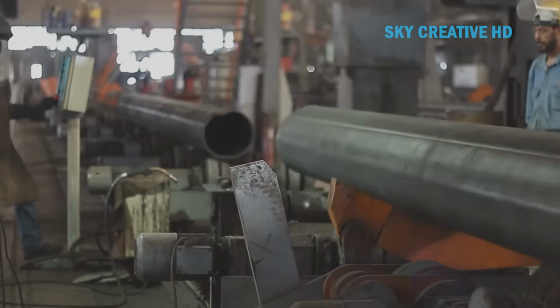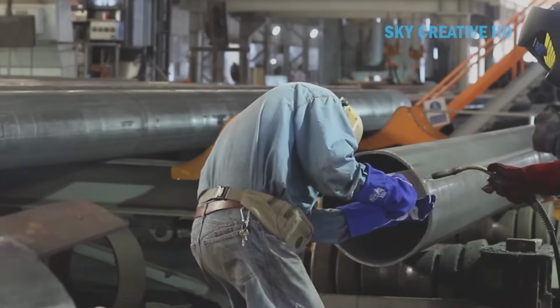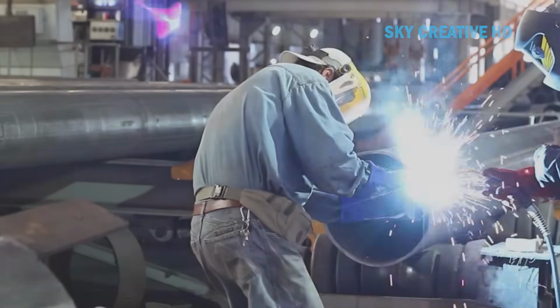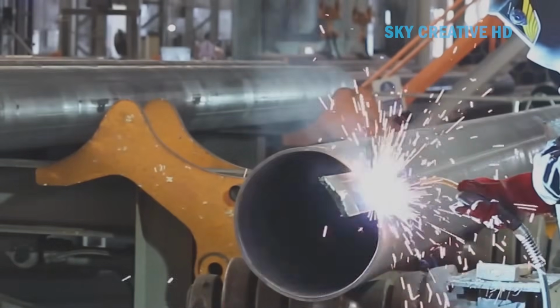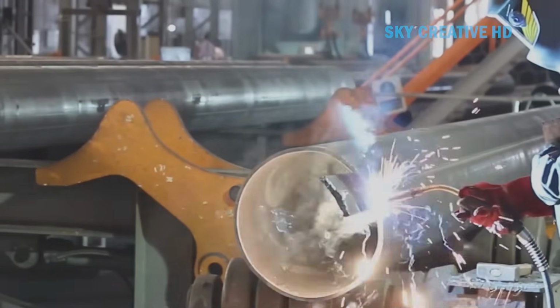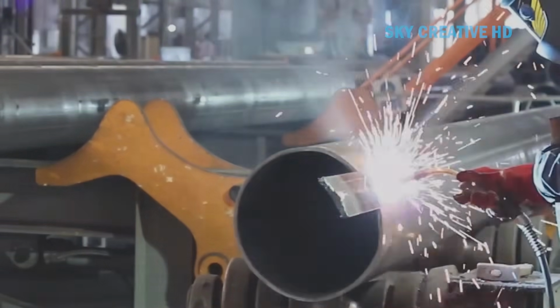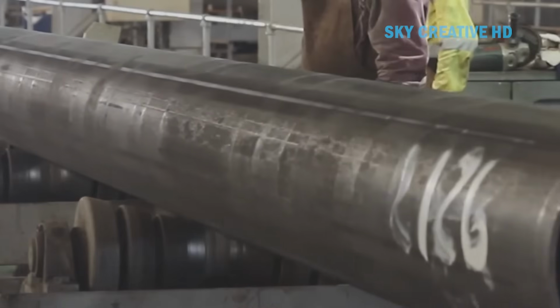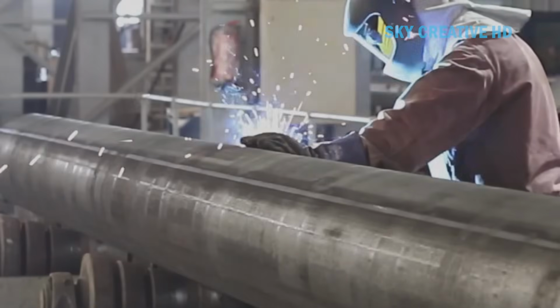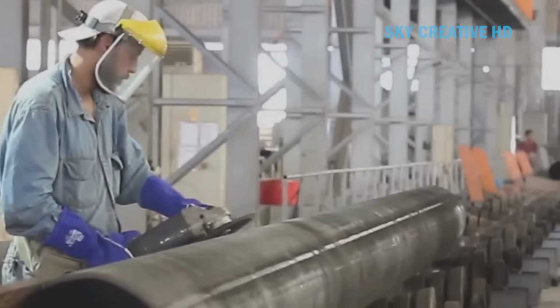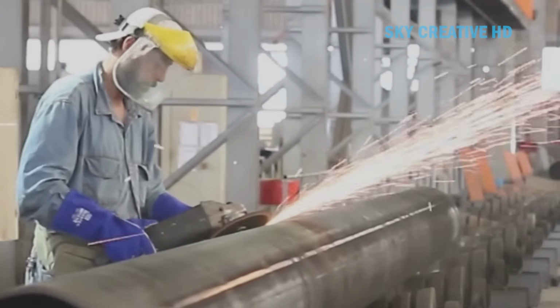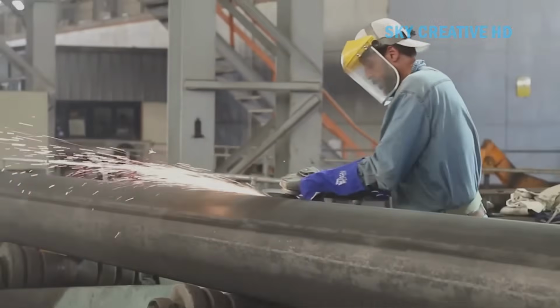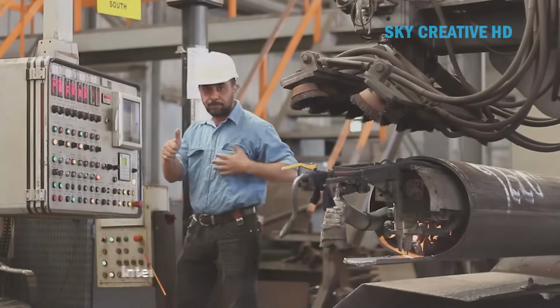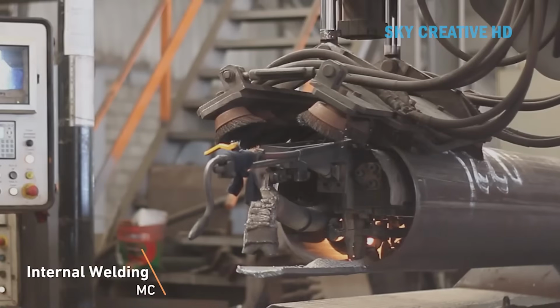Welding represents one of the most critical steps in pipe manufacturing. The systems used here employ both inside and outside welding heads working simultaneously. The outside weld provides strength, while the inside weld ensures complete penetration and creates the smooth internal surface essential for fluid flow. Welding parameters, current, voltage, travel speed, and wire feed rate are controlled to tolerances that ensure every inch of weld meets stringent quality standards.